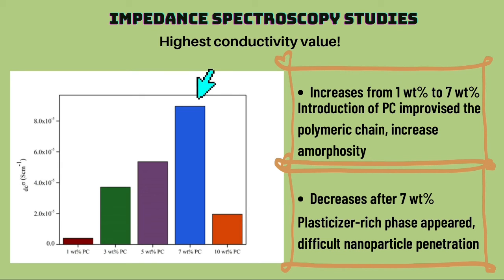You can see the highest conductivity value is at 7 weight%, which is the blue graph. From 1 weight% to 7 weight%, the conductivity increased because the introduction of plasticizer improved the polymeric chain mobility. After 7 weight%, we can see that the conductivity decreased. This is because a plasticizer-rich phase appeared, hence it is difficult for nanoparticles to penetrate the polymer matrix.